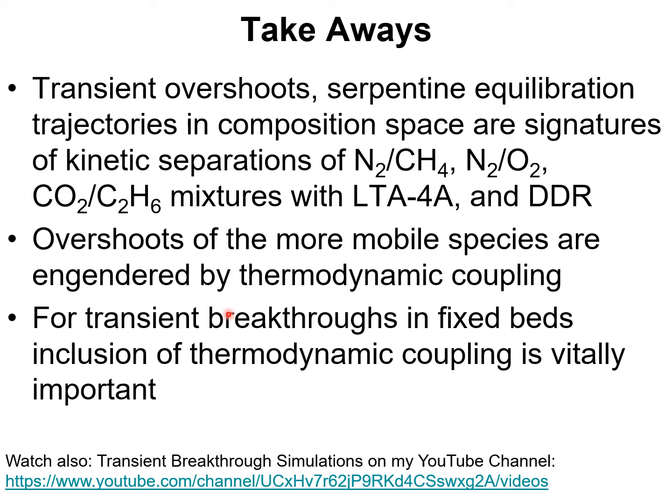Using the Maxwell-Stefan diffusion equations, we have analyzed adsorption and diffusion of nitrogen-methane mixtures in LTA4A zeolite, separation of nitrogen-oxygen mixtures using LTA4A zeolite, and separation of CO2-ethane mixtures using DDR zeolite. For all three cases, we established that transient overshoots and serpentine equilibration trajectories in composition space are signatures of kinetic separations.